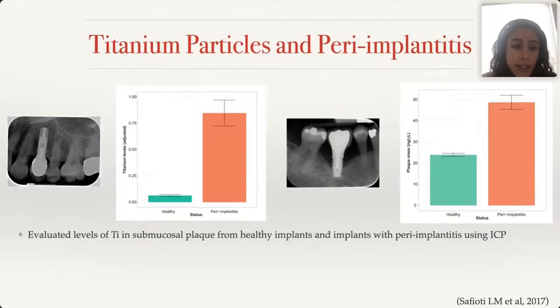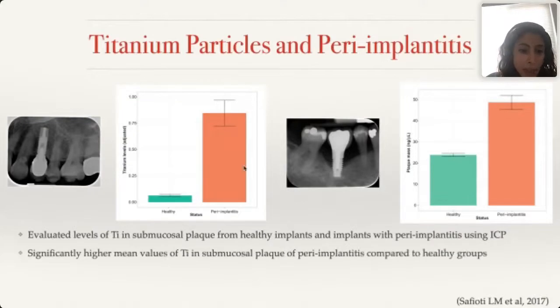They evaluated the levels of submucosal plaque titanium particles using inductively coupled plasma. They took submucosal plaque of healthy implants and also peri-implantitis cases with titanium, comparing plaque levels between groups, and measured the amount of titanium particles inside the plaque using a special instrument called ICP. What they found was significantly higher mean values of titanium in submucosal plaque of peri-implantitis compared to healthy groups.